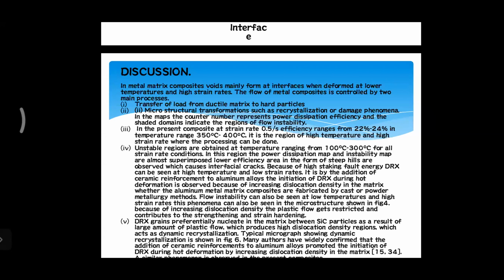At lower temperature, there is dynamic recovery of the material, that is DRV, and at higher temperature we see DRX, that is dynamic recrystallization. At higher temperature, the grains are also refined to smaller size and preferentially arranged in a proper manner, but in the case of the matrix, they nucleate around the SiC particles. This is the part responsible for cracking or deformation of the material. Sometimes the SiC particles hinder the flow of the material, and sometimes they create a very good flow of the material.